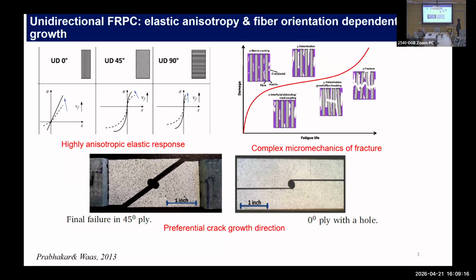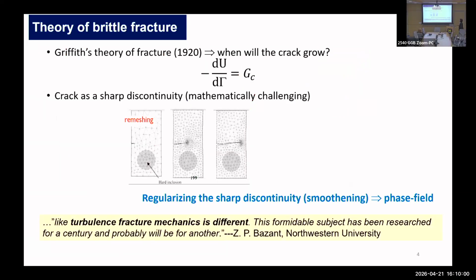Okay. Similarly, if you see the fracture behavior, and by the way, this experiment was done here at the University of Michigan in Professor Waas's lab, where basically they considered open hole tensile samples with fiber oriented at different angles with respect to the loading direction, and these are open hole tension, so the samples were pulled along the horizontal direction. And you can see the crack starts from the notched edge and then propagated following the fiber path. Okay, so highly anisotropic phenomena even when the external load was purely tension dominated. So characterizing that and incorporating that in a modeling environment has been challenging. Of course, cohesive zone model has been used as a recourse, but there were issues.